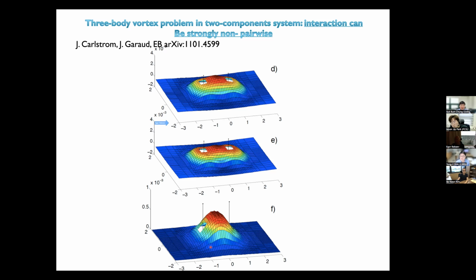But yeah, my question is about, if you have a vortex lattice in this type 1.5 superconductor, I guess one characteristic feature would be how the stability of this kind of lattice would depend on the lattice parameter. But without changing the lattice constant, would there still be some way to figure out whether this is type 1.5 stable, just by looking at its collective mode?